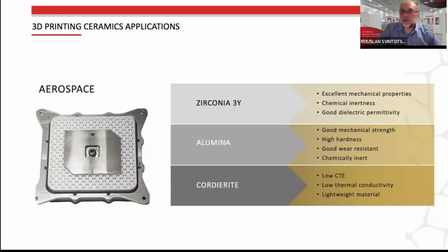Materials are very important. We were speaking about the materials for the conventional space, but in general, we could highlight some of the materials used for space applications. For aerospace, we use a lot of zirconia 3% yttria. It has excellent mechanical properties, good chemical inertia, and good dielectric properties. Alumina is used in a lot of cases, not only in aerospace, but also in general industry applications. It also has good mechanical properties, high hardness, is chemically inert, and is also cheap, much cheaper than zirconia. Cordierite is a very interesting material we have in our standard portfolio. This material is rigid, has a low coefficient of thermal expansion, and is lightweight. Usually it's used for some optical applications because of its rigidity and low CTE.